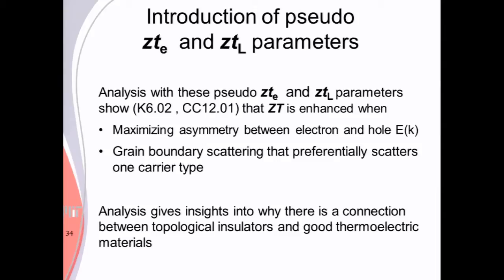So in our study, Shuang will be talking about this in these 2 talks that are cited here. He will explain what it takes to maximize these individual ZTs so that you can get a more rapidly convergent total ZT, which is the sum of these 2 individuals, the electron and lattice contribution. So one thing he finds is you want to have the biggest difference, asymmetry, in the electronic E versus K. That's an important ingredient. We sort of knew that before, but I think that we have it more quantitative now than we had it before.